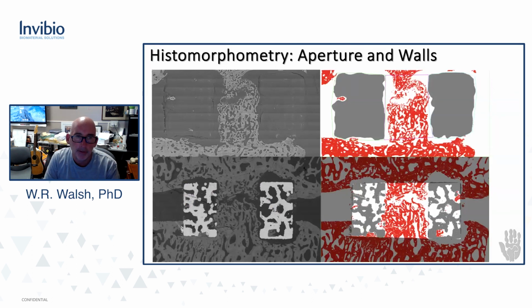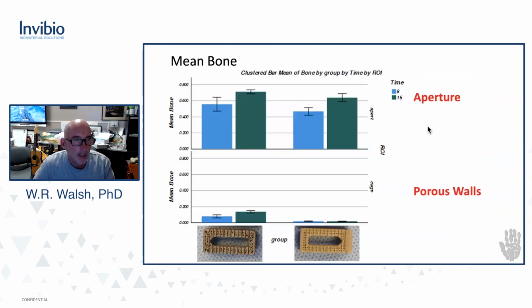We also quantify everything histomorphometrically. So we look at what's in the walls, what's in the aperture for both types of implants. And we look at how much bone is in the aperture. We've got titanium on the left, it progresses with time. PEEK on the right, it progresses with time. How much bone is in the walls? A little bit with PEEK, a little bit with titanium.